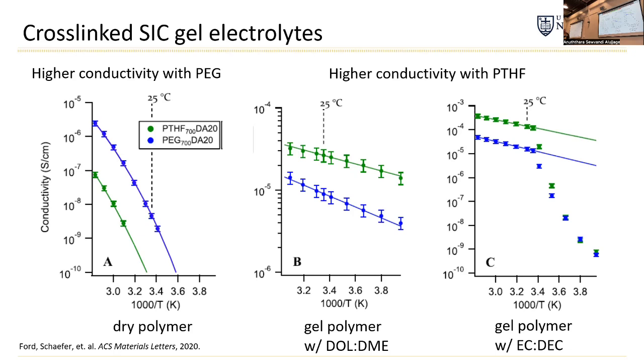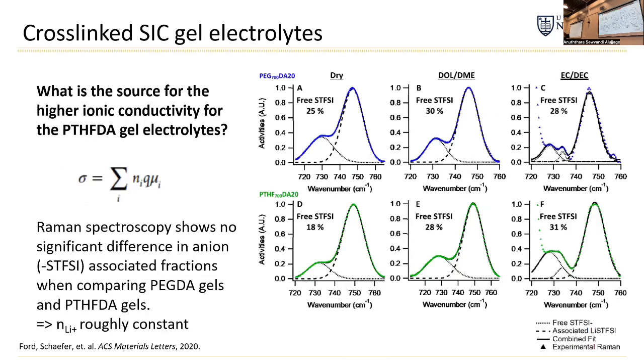And we were actually kind of surprised by this because PEG diacrylate gel electrolytes are used in the literature. There are so many papers. You can find so many. You just Google PEG, polymer, gel, electrolyte, and you're all over the place. But with just a really simple change, by lowering the oxygen density, somehow we're getting a much higher conductivity. And so he tried to figure out why this was.